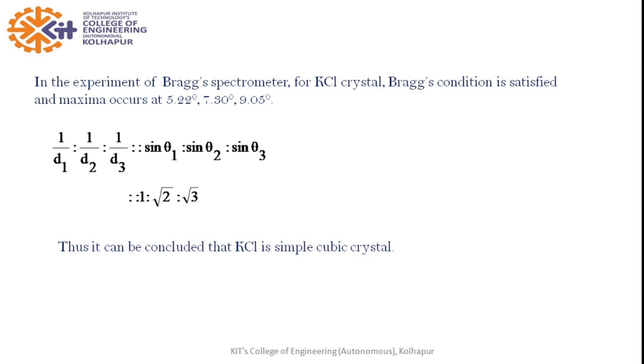Bragg's condition 2d sin(theta) = n*lambda is a very important condition, but it is not the only condition. Such diffraction data is available for all crystals through JCPDS/ICDD — the Joint Committee for Powder Diffraction Standards, formed in 1941, and renamed in 1978 as the International Centre for Diffraction Data. This data is available for thousands of materials, providing interplanar distances and relative intensities, which we compare with our experimental data.